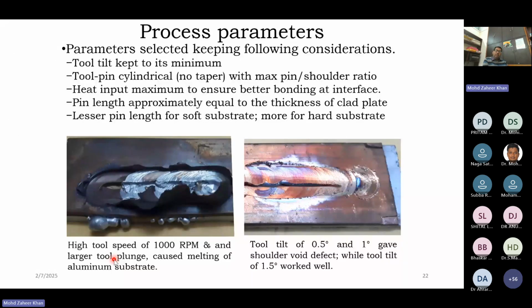Setting of the process parameters was another problem. As you might be aware, the friction stir welding process requires several process parameters to be set. That includes the tool RPM, the speed at which the tool has to be traversed, and the tilt angle, because the tool is not vertical to the plane of the plate; rather it is tilted on the side opposite to the side in which you are moving the tool. So if you are moving the tool from left to right, the tool will be slightly tilted on the right side.